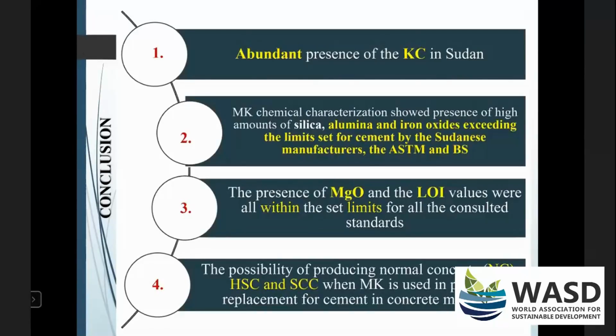And these are the major oxides that we are looking for. At this point, we were very happy with these amounts, and we were expecting good results, as these are early indications for the suitability of this material. Also, we found out that the presence of magnesium oxide and the loss on ignition values were all within the set limits for all the consulted standards. It was also evident the possibility of producing normal concrete, high-strength concrete, and self-compacting concrete.